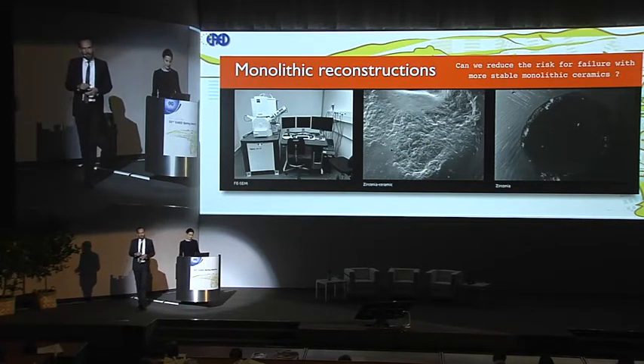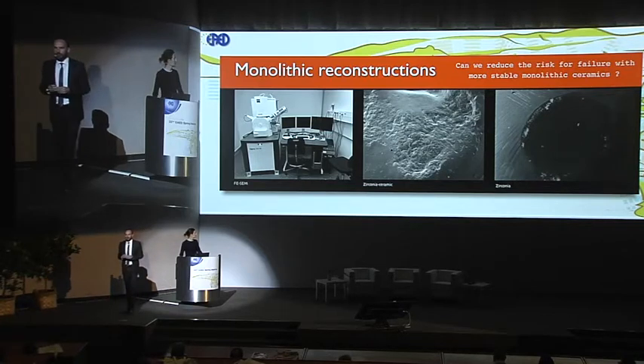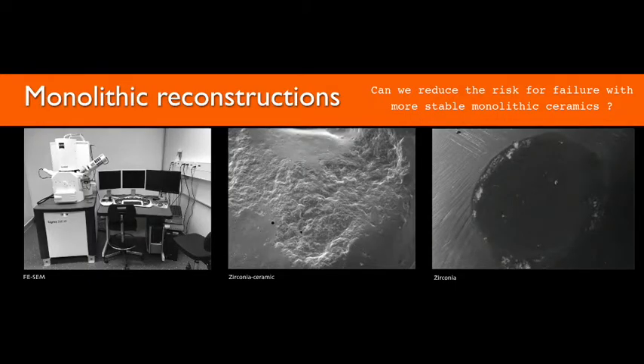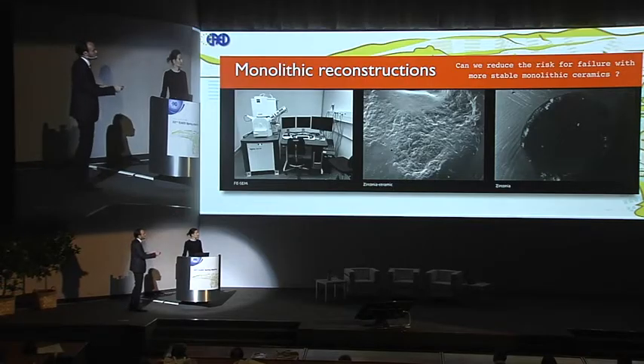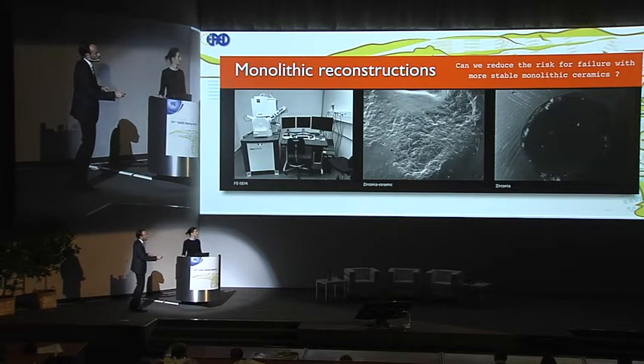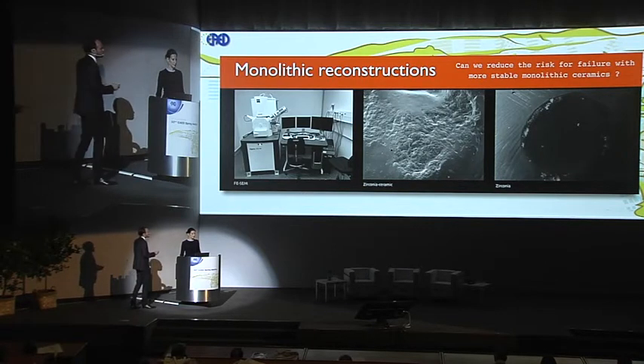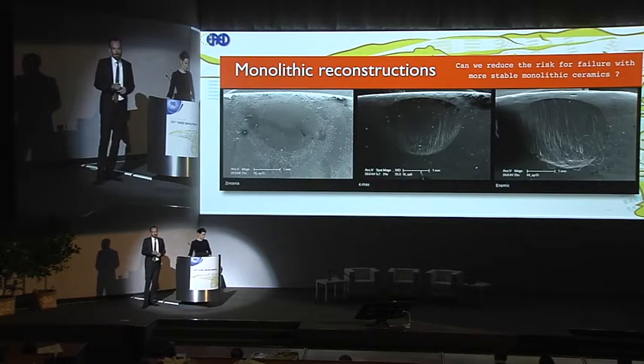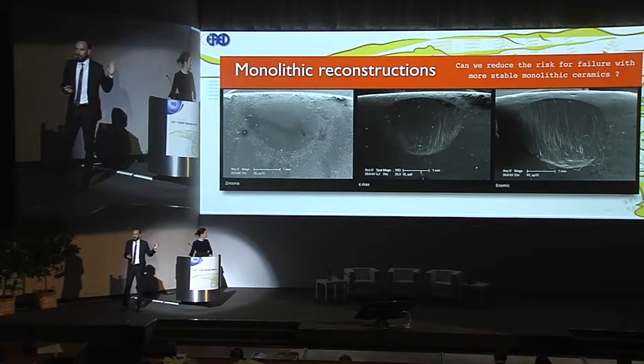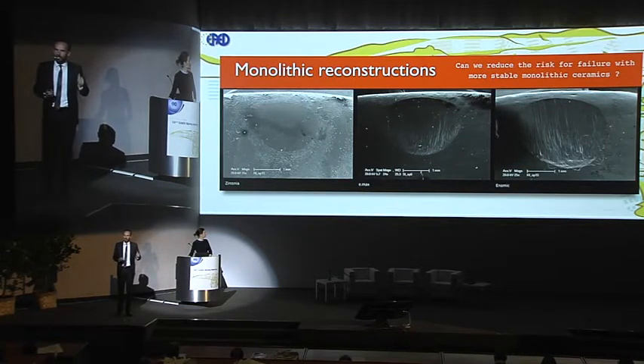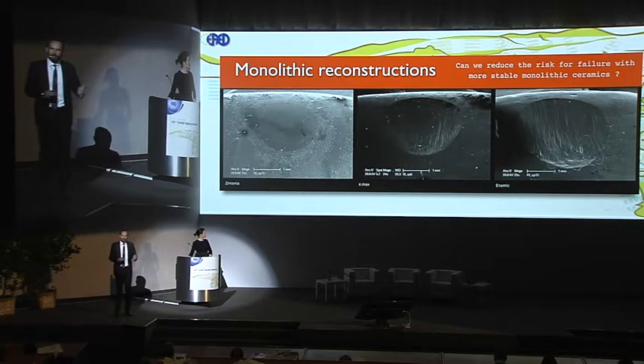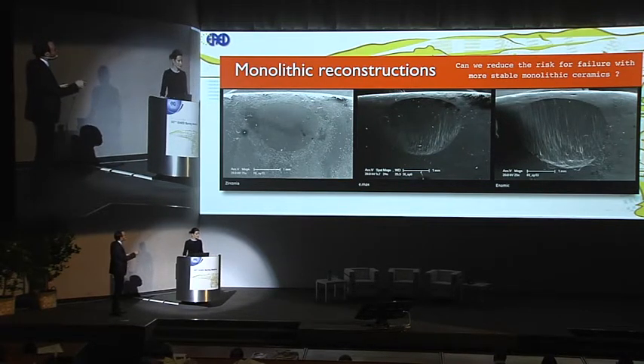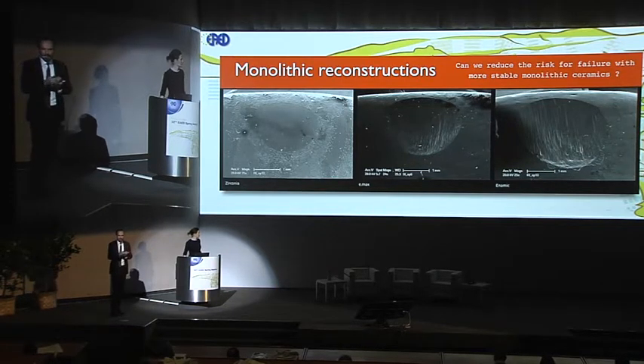Exactly. What you can see in the center is basically a conventional veneered zirconia reconstruction with glass ceramic. And on the right-hand side, you see the monolithic zirconia crown after 1.2 million cycles, which basically reflects 5 years. You see this looks more or less like the Swiss Alps, and this looks like a clean mirror image, no porosities, nothing inside. And this is the three study group samples that we can show you, and there you also will understand why the zirconia, even being such a hard material, behaves so well to the antagonist when it comes to the wear pattern, because it's just perfectly polished on its surface. However, you see the hybrid just basically degrades itself.